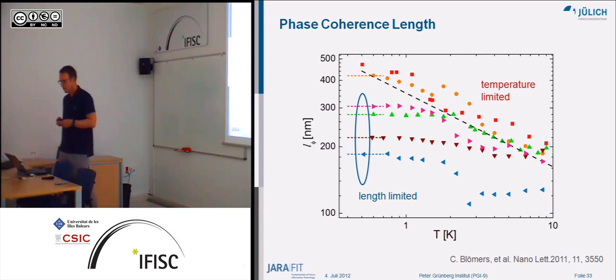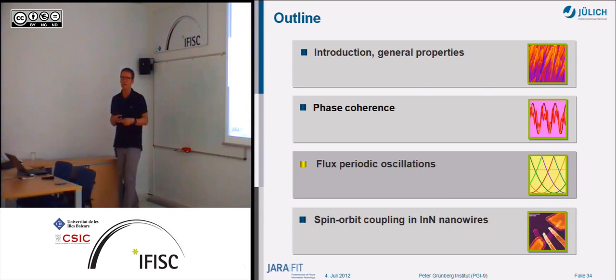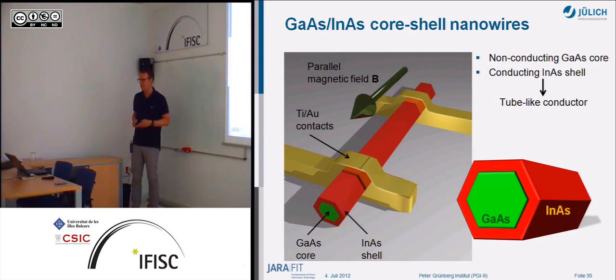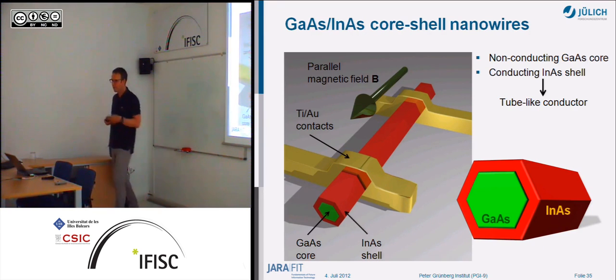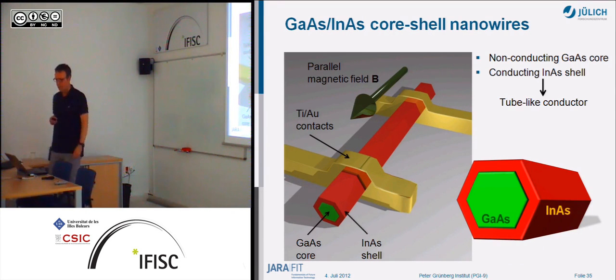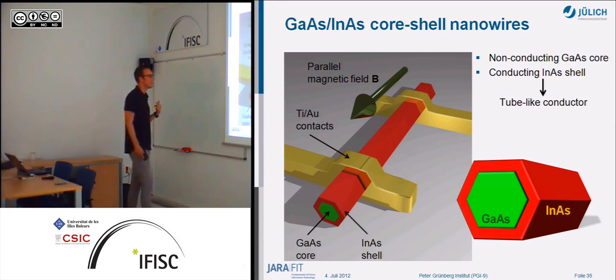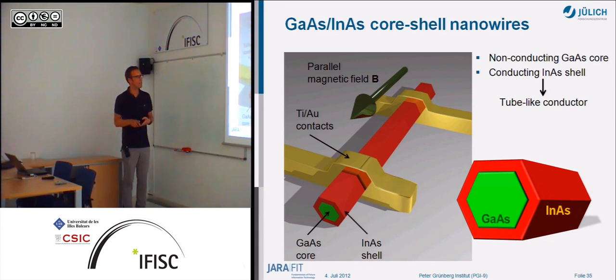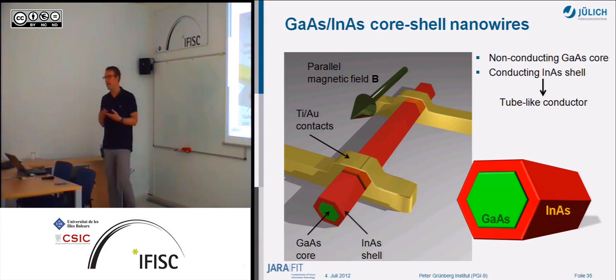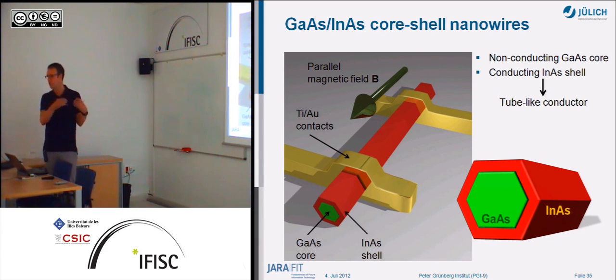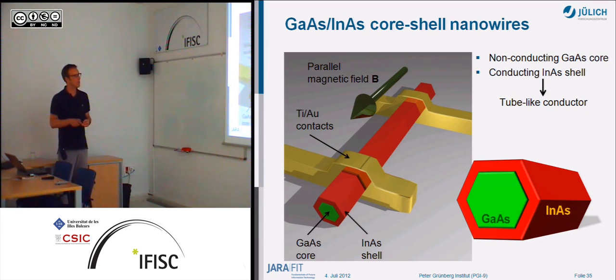So that's what you have in these nanowires. That's a typical length scale where you have phase coherence phenomena in the nanowire. So let's move over to more fancy structures. What we worked on recently were core shell nanowires, where we have the gallium arsenide, which is non-conductive. It's a high bandgap semiconductor. I told you before, you don't expect any electrons here in the nanowire, but we wrap around some indium arsenide